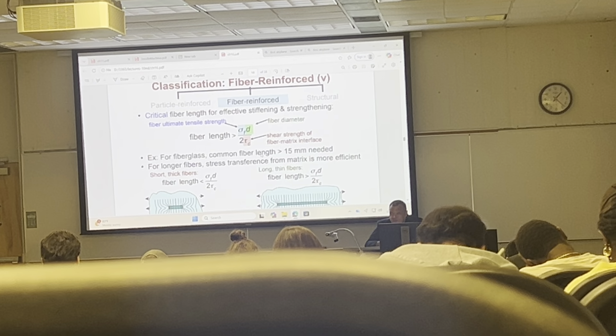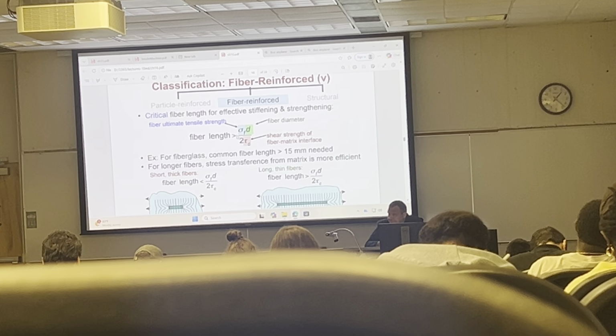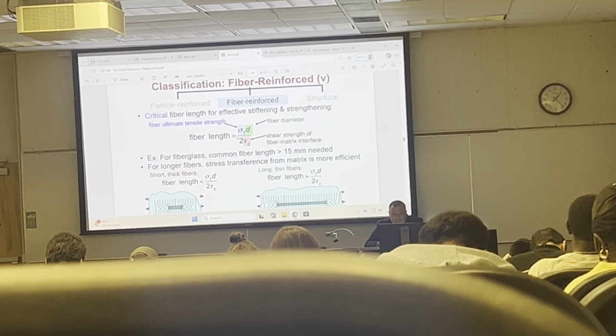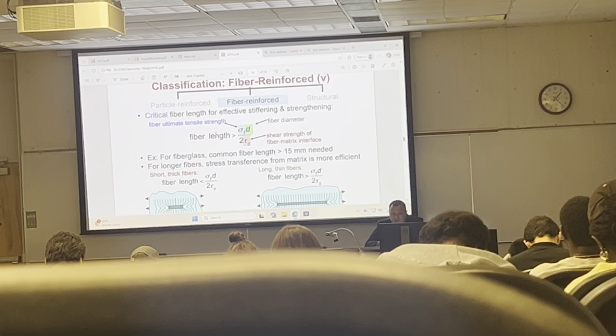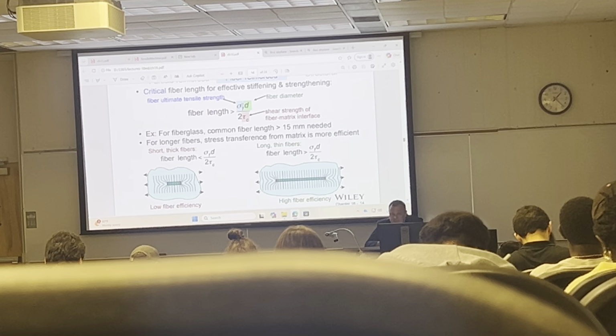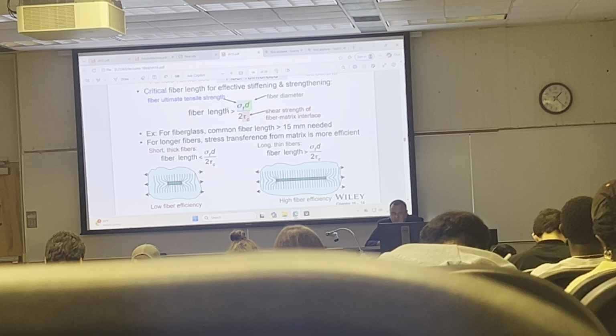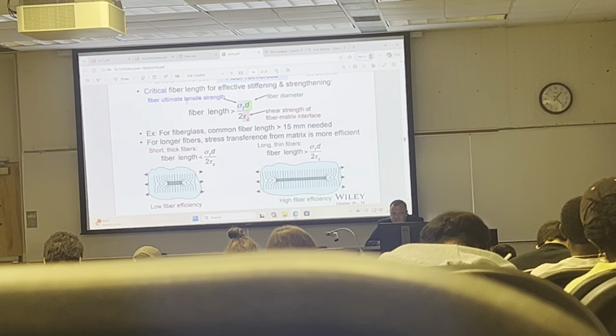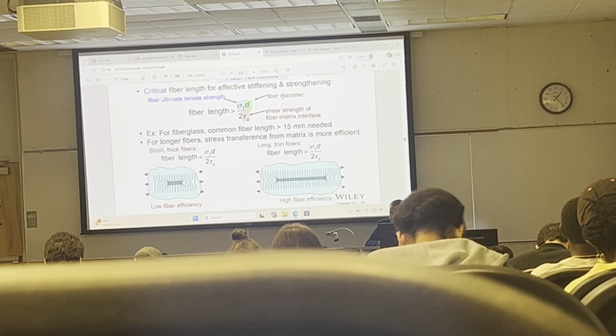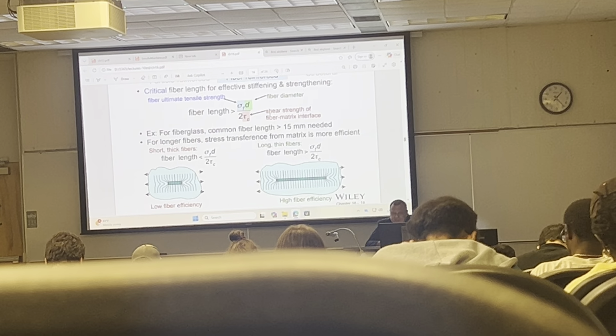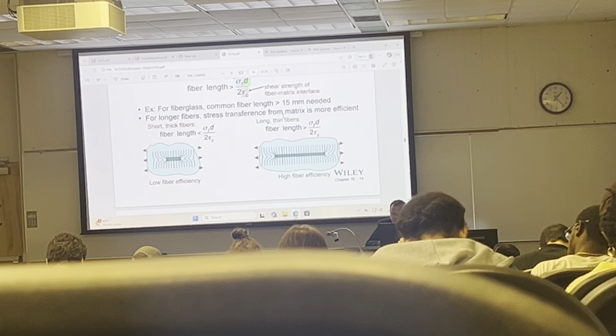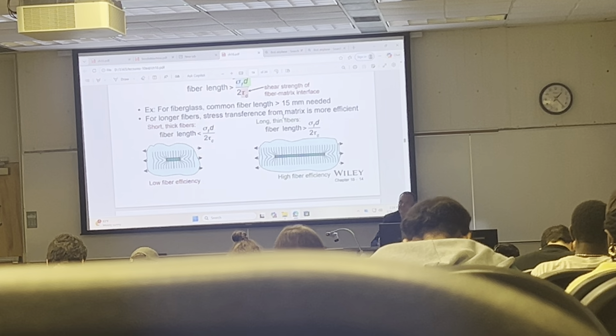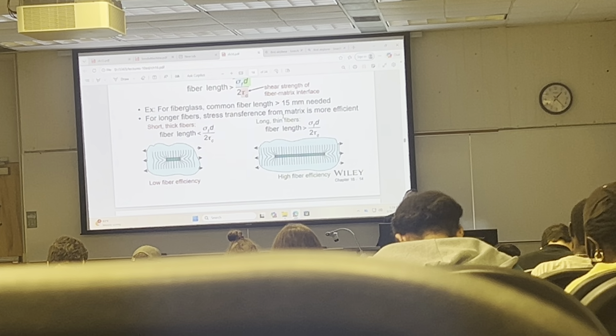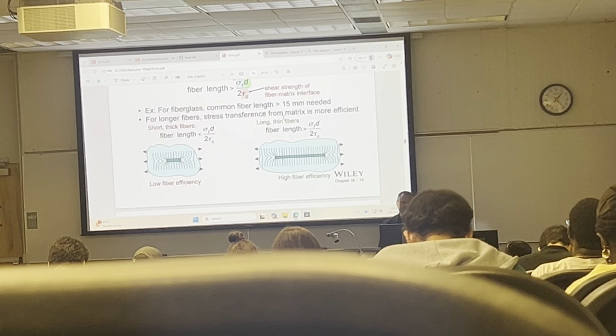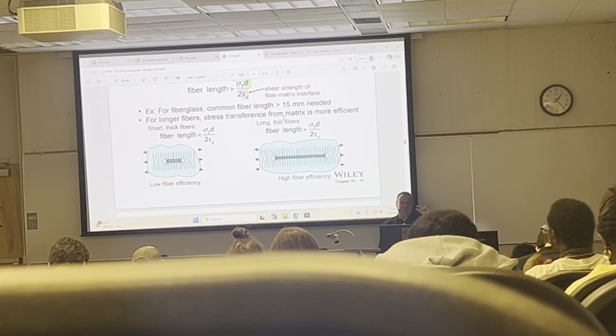Let us consider a very important technological parameter, which is the fiber length. And the idea is to increase the strength. So if the fiber length is greater than sigma f d over 2 tau sub c, where sigma f is the ultimate tensile strength of the fiber, d is the fiber diameter, and tau sub c is the shear strength of the fiber matrix interface. And typically it's arbitrary. So if the fiber length is greater than 15 millimeters, then you would have the strengthening effect.